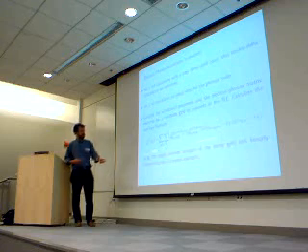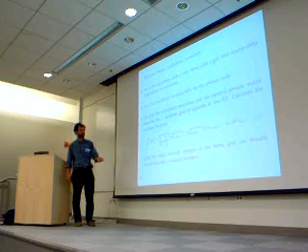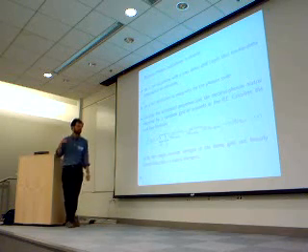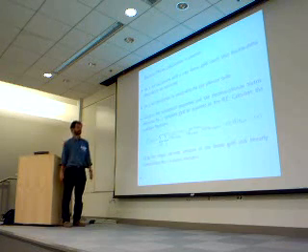And when you calculate this integral, you need to perform a double delta integration. So here you need to put very many k points. So you use the k points of the band structure that you have calculated accurately for many k points here.